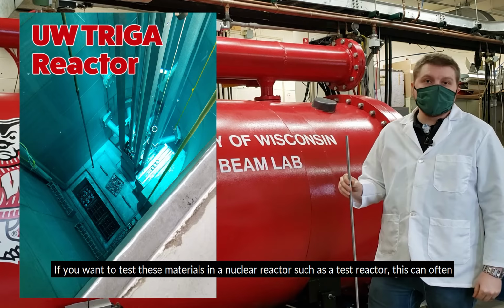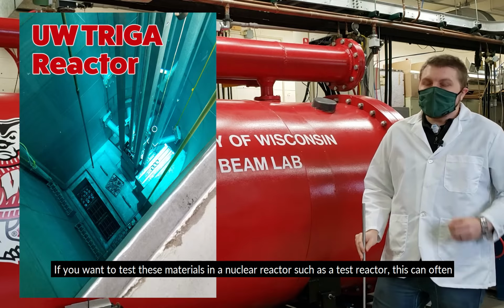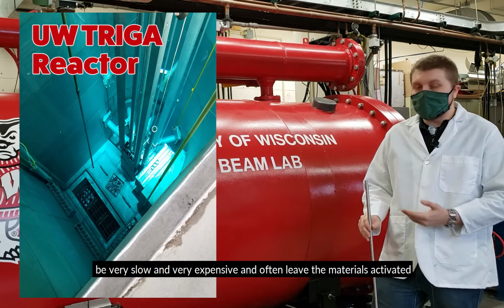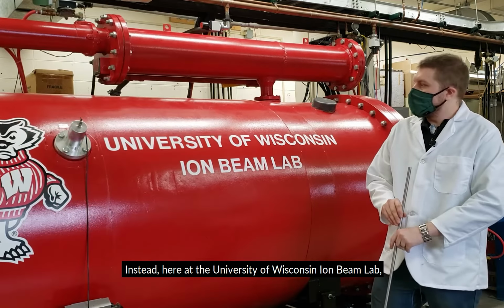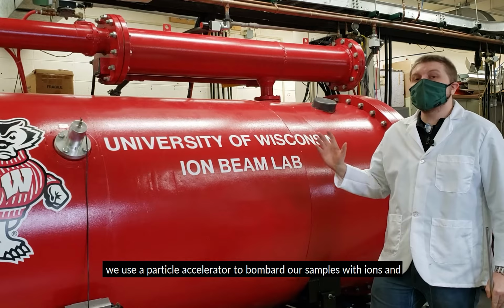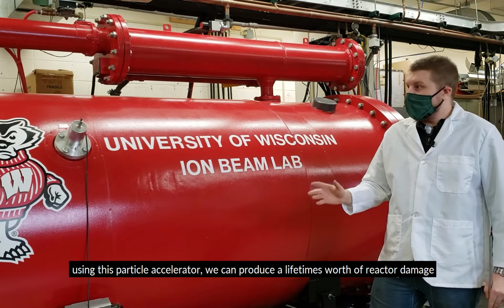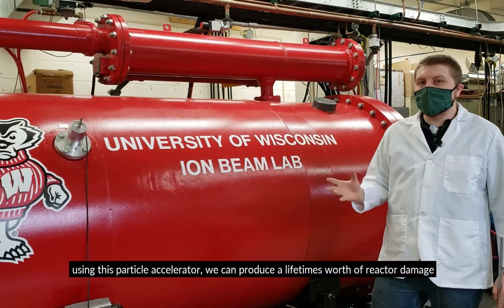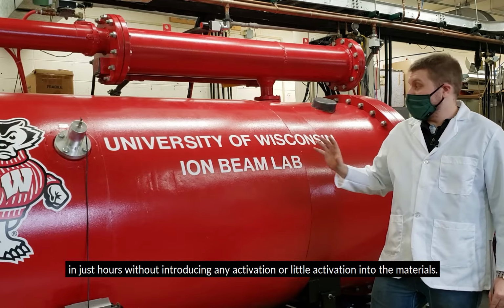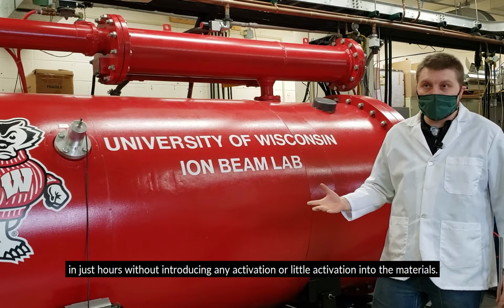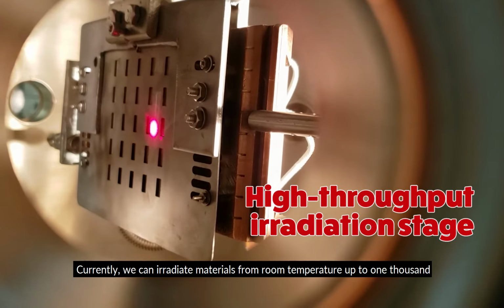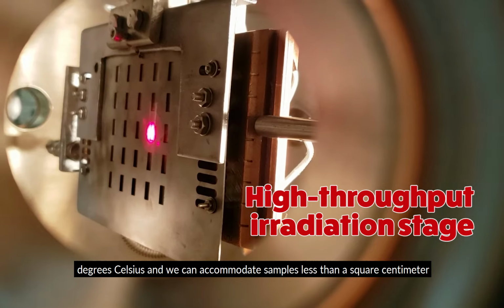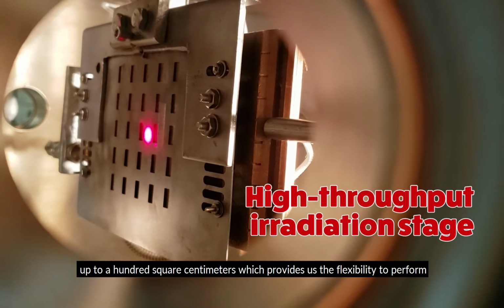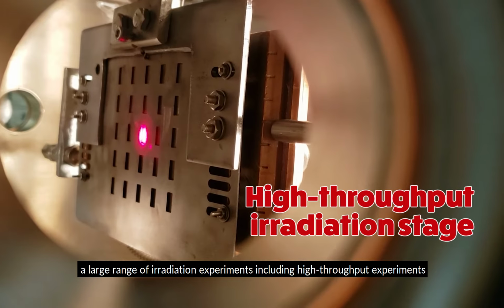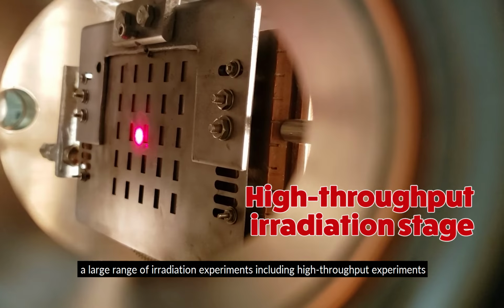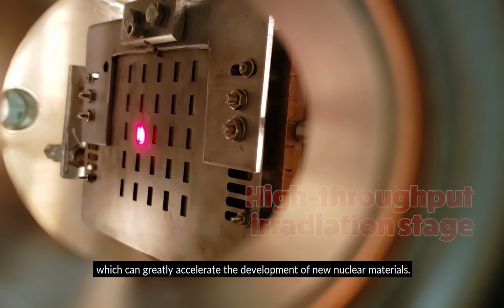If you want to test these materials in a nuclear reactor, such as a test reactor, this can often be very slow and very expensive, and often leave the materials activated and difficult to handle afterwards. Instead, here at the University of Wisconsin Ion Beam Lab, we use a particle accelerator to bombard our samples with ions, and using this particle accelerator, we can produce a lifetime's worth of reactor damage in just hours without introducing any activation or little activation into the materials. Currently, we can irradiate materials from room temperature up to 1000 C, and we can accommodate samples less than a square centimeter up to 100 square centimeters, which provides us the flexibility to perform a large range of irradiation experiments, including high throughput experiments, which can greatly accelerate the development of new nuclear materials.